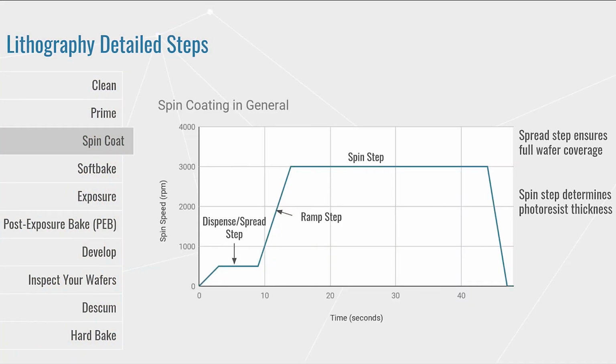This graph describes the spin speeds during the coat process in more detail. During the dispense step, the wafer is spun slowly so the resist can spread and cover the sample surface. During the ramp step, the speed is increased to reach the spin step speed. This ramp rate can be high for thinner resists, but may need to be lower for thick resists to ensure good coat uniformity. In the spin step, the resist thickness is set.